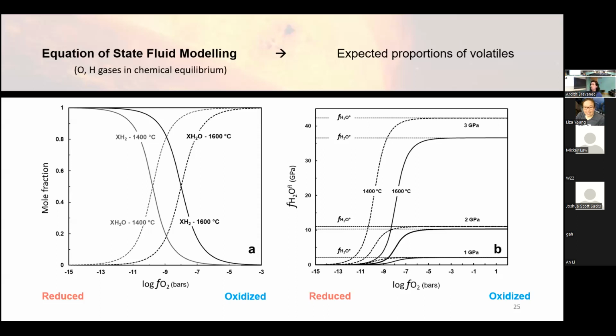So to start off, it's instructive to start with just basic fluid models, absent again all of the geology, just looking at the equation of state modeling for, in this case, just OH. And what you see here is as you get more reduced, to more negative oxygen fugacity, water becomes diminishingly small in proportion, and basically the fluid speciates entirely to hydrogen. What this means too is that my earlier correlation matrix was flawed when I considered oxygen fugacity in terms of water fugacity, because we wouldn't actually have water fugacity at all in an extremely reduced system. You can see that given there on water fugacity, superscript fluid. It actually drops to 0 in a sufficiently reduced system. And in fact, the important fugacity to consider is going to be hydrogen fugacity.